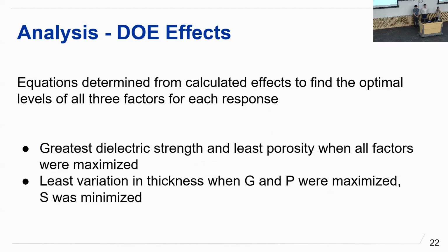So we input the effects we calculated into that general equation that Alex showed you guys earlier to find the optimal levels of all three factors for each response. We found that the greatest dielectric strength and also the least porosity occurred when all factors were maximized. And we found the least variation in thickness occurred when the gas flow rate and deposition passes were maximized, but when stage speed was minimized.